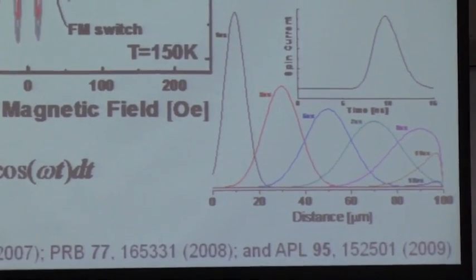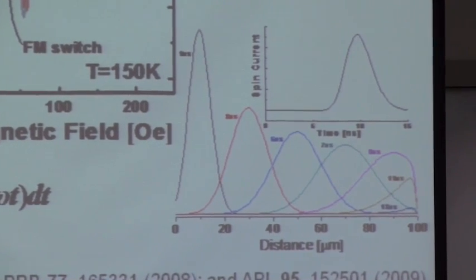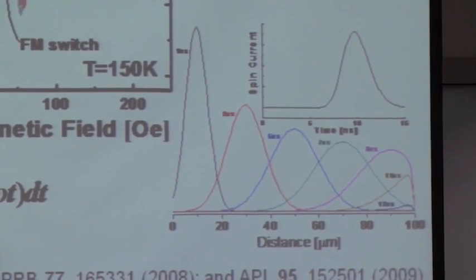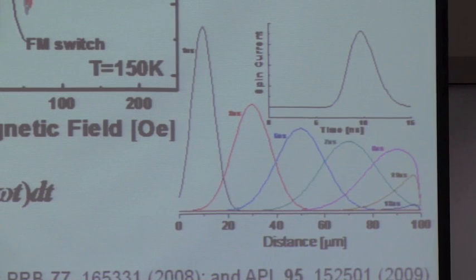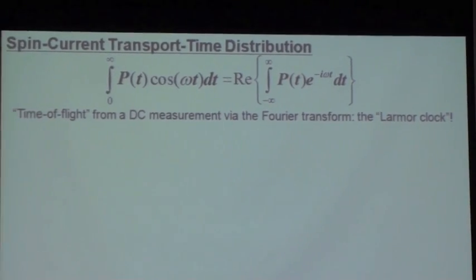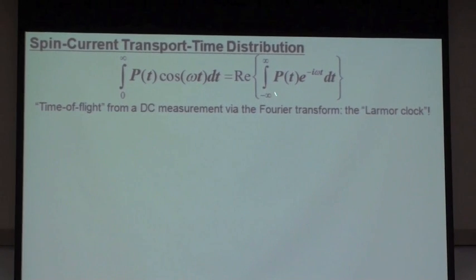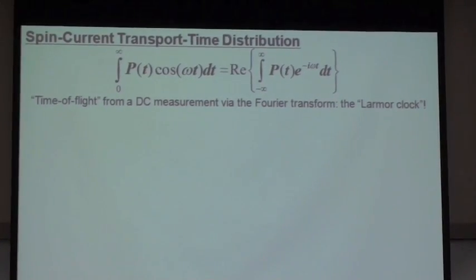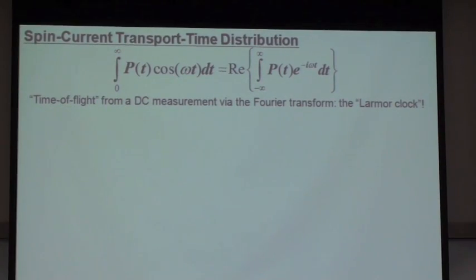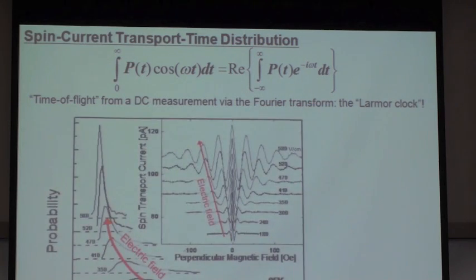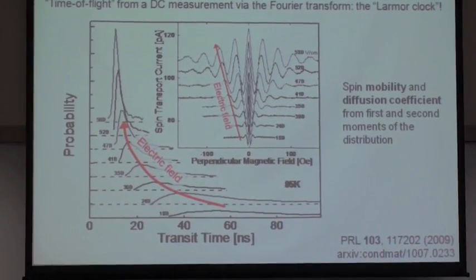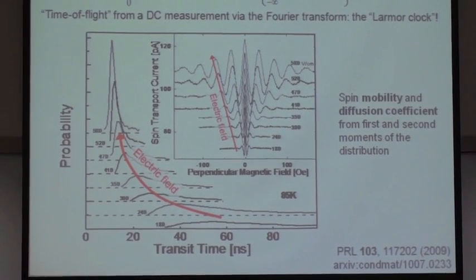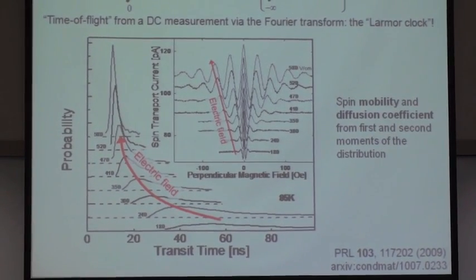But what we like to do even more is to be able to start with our empirical data, and recover from it an empirical spin transport distribution without any model fitting. And it turns out you can do that as well because, of course, this is just the real part of the Fourier transform of the arrival time distribution. And so we can invert that transform, take the inverse transform, to recover the empirical transit time distribution for our spin current. So the idea here is illustrated here.